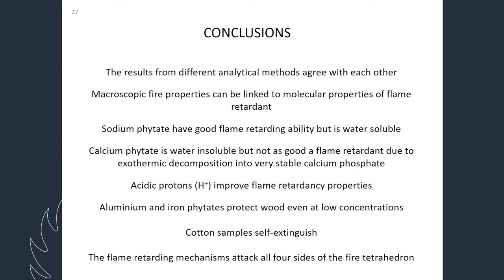But the problem with sodium phytate is that it's water soluble. So we want to have a material that is not water soluble, and that is calcium phytate. But it was not as good as a flame retardant because of this exothermic decomposition into stable calcium phosphates. And we can see that when we have these acidic protons available in the structure, then we have better flame retardancy because then we have better ability to char the wood.